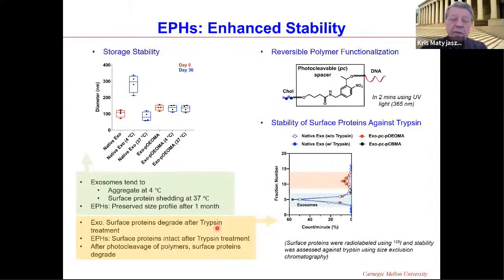The stability is much stronger after grafting. This is what happens with the native exosomes: after 30 days, they aggregate, and these exosomes with polymers stay intact at lower or higher temperature as well. Now, you can attach polymers, but you can also remove polymers. This is done by using this photocleavable linker, and in that case, after the degradation, you can remove the polymer chains completely.